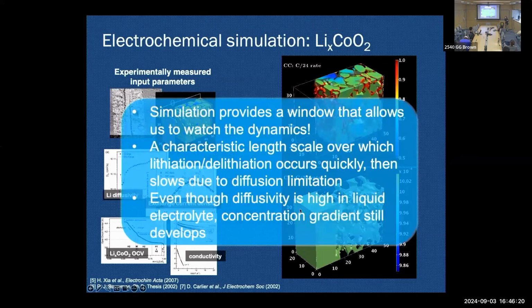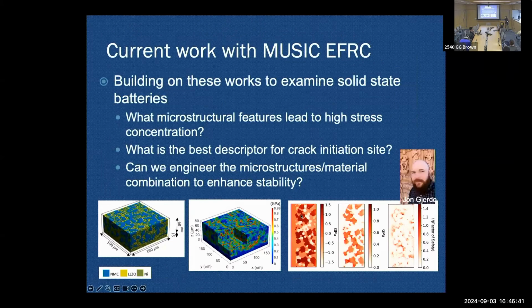Even though the diffusivity is high in liquid electrolyte, and people thought you don't have to worry about the depletion of ions or the concentration gradient of the ions in the electrolyte, it is still an issue. Those are things we learned very quickly. Currently, we are working within the MUSIC EFRC, building on those works to look at solid-state batteries. All solid-state batteries are difficult to make work because there are stresses in there, and you can form cracks and things like that. Jordan is looking at all of that data, and at what features in the microstructure and material combination lead to propensity for cracking. That's what he's studying.